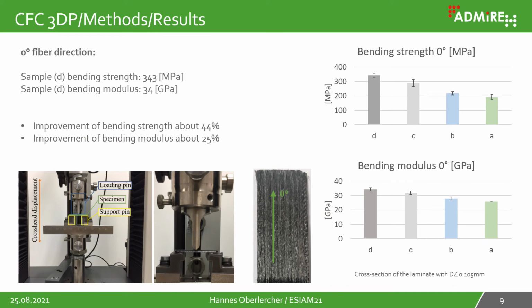Next, we produced some 3-point bending test samples, some with 0 degree fiber direction, some with 90 degree fiber direction, from every test sample from A to D. And sample D showed us the best bending properties. The bending strength was about 343 megapascal and the bending modulus about 34 gigapascal.